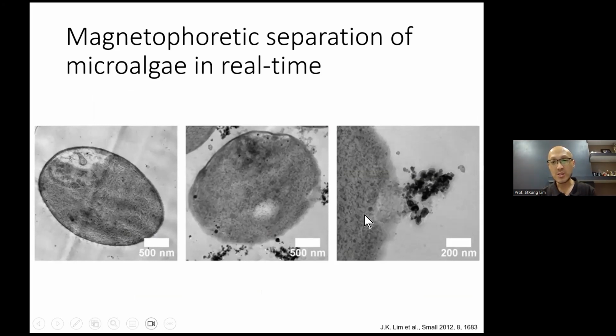And actually, these results reveal to us two possibilities. The first possibility is straightforward. By using surface functionalized iron oxide particles, we could impart magnetic properties onto the cell, and that's why we can separate them by using a magnetic field. The second one is, in addition to unidirectional separation, that means we can only separate them in one direction, if we really think about it, if the particles can attach to the cell, we could now rely on these magnetic particles to guide the motion of the cell, which means we could really move the cell by using a magnetic field.